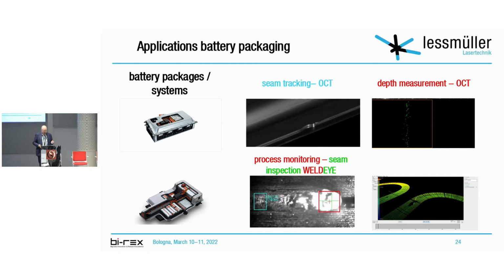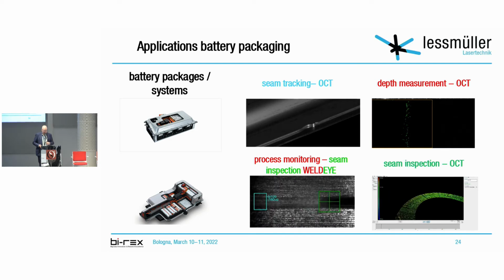We can also work with material combinations, as we've heard today, where you need assist wire. We still have our camera-based welding system that identifies the wire and the position of the process, and then looks at the final result. And we can do seam inspection with OCT running over the part and looking for failures in the seam, like you see here, the black holes.